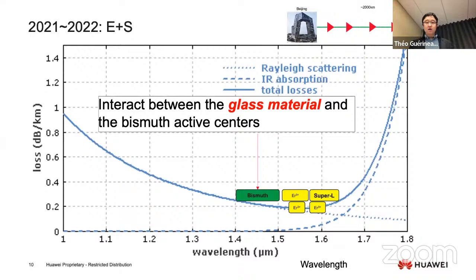And in addition to the erbium EDFAs for C and L band, currently telecommunication people are looking for possibilities of using the S band and E band, which is located between 1.4 micron and 1.5 micron. So again, in this wavelength region, erbium can't work. So currently we are working on the bismuth. The bismuth-doped fiber amplifier was invented back in 2006 by the famous Professor Dianov, who passed away two years ago in Russia.